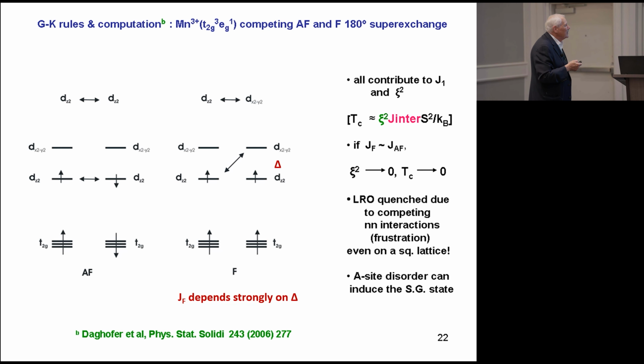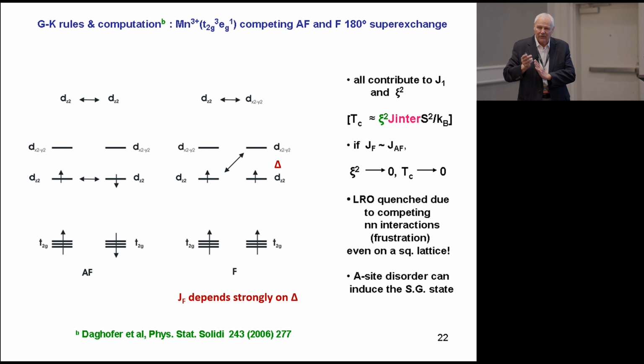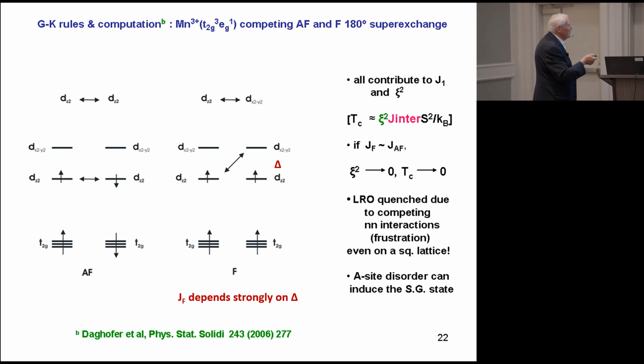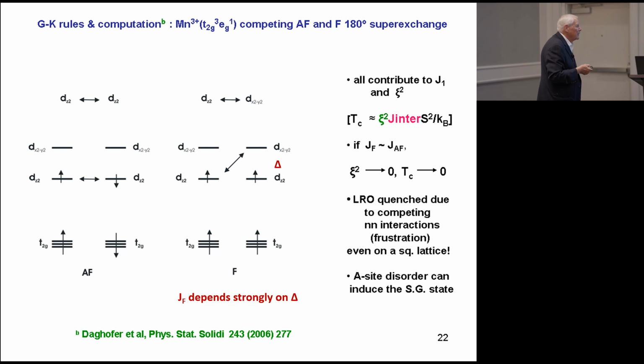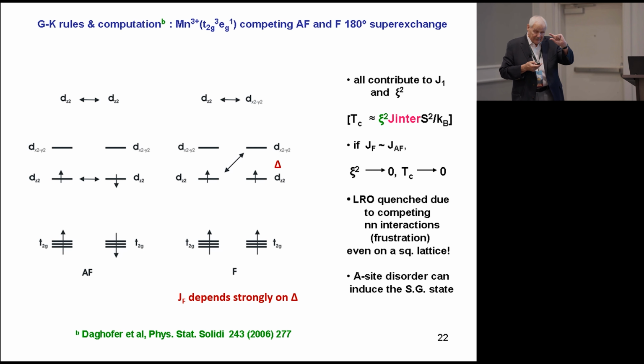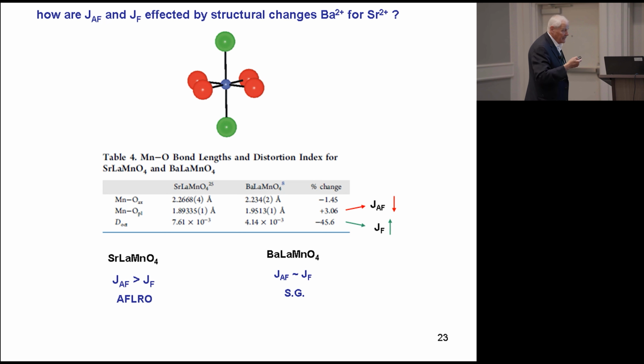With manganese 3+, you of course have a Jahn-Teller ion and you have a distorted octahedron. And so the splitting pattern of the eg orbitals looks like this, where the z^2 level is below the x^2 minus y^2. And there's an antiferromagnetic pathway. And there's also a ferromagnetic pathway where the spin is transferred to the empty x^2 minus y^2 orbital. However, this pathway is less favorable in general because there's an energy splitting between the two due to the Jahn-Teller distortion. So in the all strontium phase, the antiferromagnetic interaction wins out. But in the all barium phase, there's a chance that the ferromagnetic interaction will be competitive.